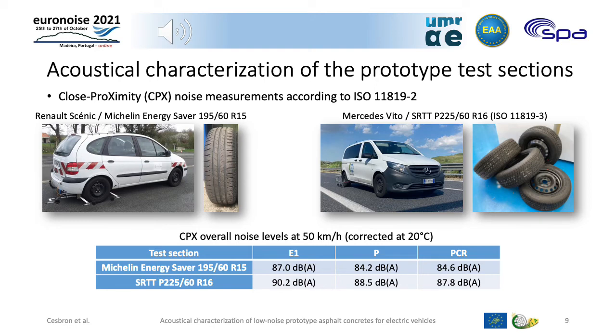Firstly, close proximity measurements have been performed according to ISO 11819-2. Two kinds of configuration have been tested. The first configuration was a Renault Scenic fitted with Michelin Energy Saver tires. The second configuration was a Mercedes Vito fitted with SRTT tires conforming to ISO 11819-3. In the table below you can see the CPX overall noise levels at the reference speed of 50 km/h, corrected at the air temperature of 20 degrees.